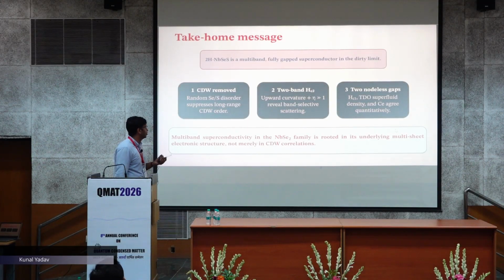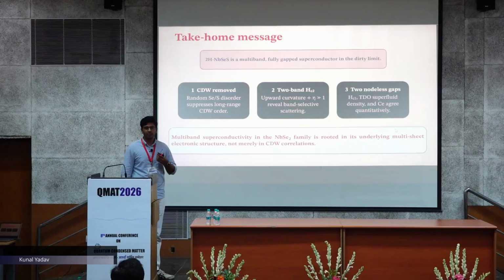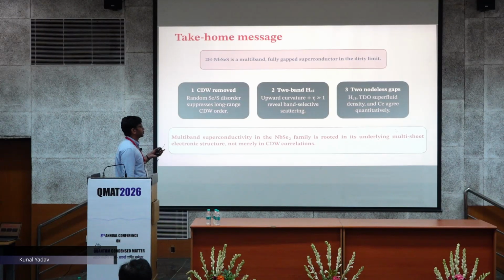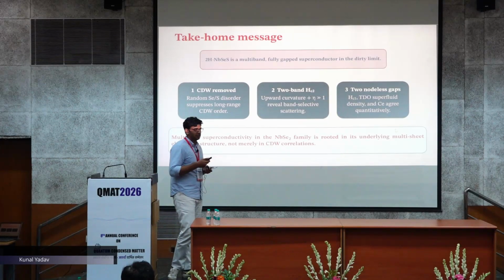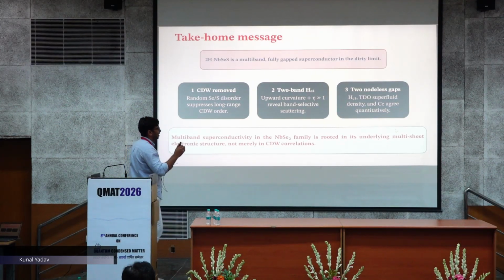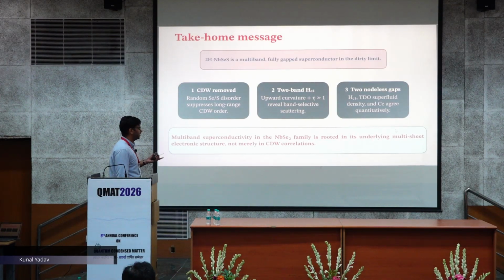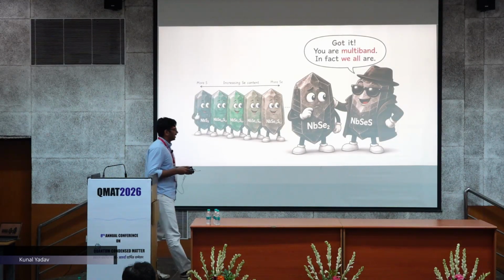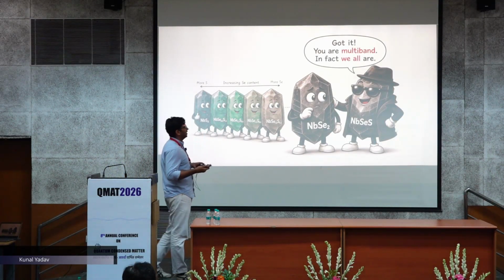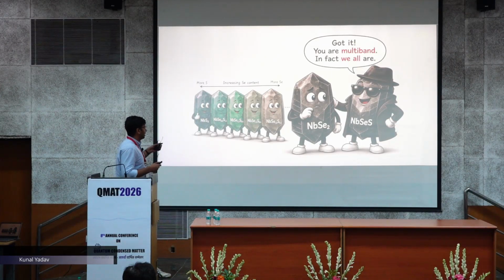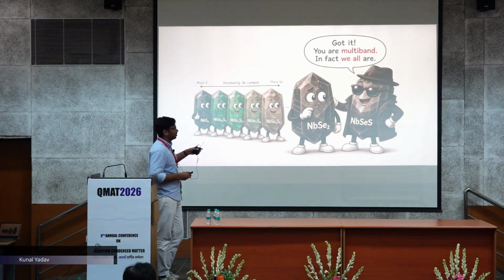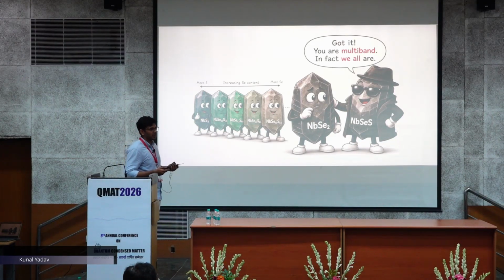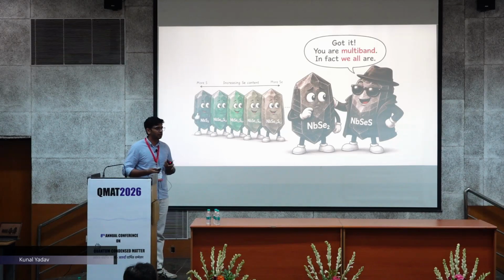First, we have removed the CDW. The random substitution of sulfur and selenium removes the CDW there, and then the two-band fitting in HC2 shows multiband superconductivity, also with three different measurements of HC1, superfluid density of the tunnel diode oscillator, and the specific heat, which also agree with the multiband superconductivity in NbSeS. In fact, the whole series from NbSe2 to NbSeS is a multiband superconductor. It is not due to a mimicry of CDW there.